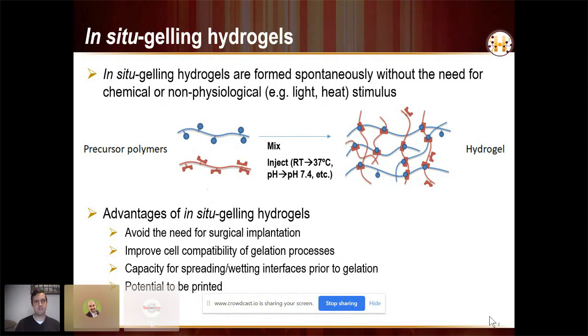And again, beyond just avoiding the need of surgical implantation, there are other advantages. If we're trying to deliver cells, if we do that in a very viscous polymer solution, for example, like a shear thinning hydrogel, a lot of stress is placed on the cells, and this results in relatively low cell viability at the end when we actually get it inside the body. Whereas here, the viscosity of the precursors is much less.